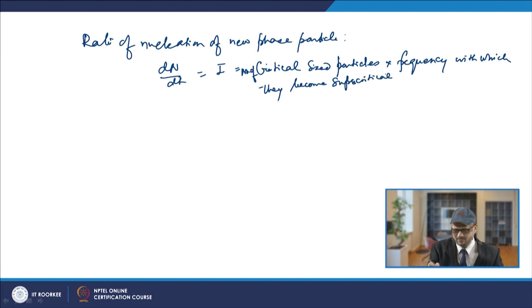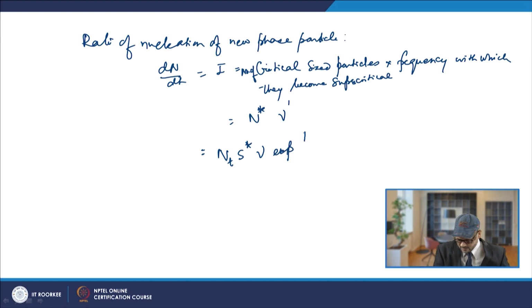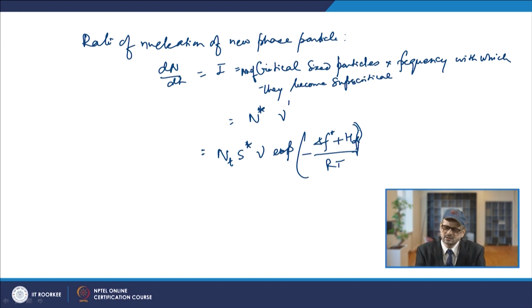Supercritical. So, we have got the expression for that, and it will be n star and nu prime. So, it will be n_t s star nu exponential minus of delta F star plus H_d, divided by RT. So, that basically is talking about the expression for the rate of nucleation, and what we see is that the pre-exponential term value is coming in the range of 10 raised to the power 42 meter raised to the power minus 3 per second, and then depending upon these values your nucleation rate will be defined.